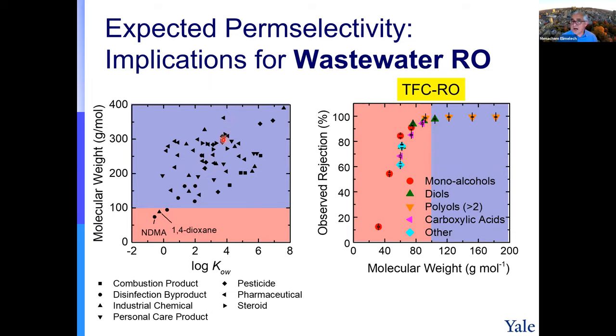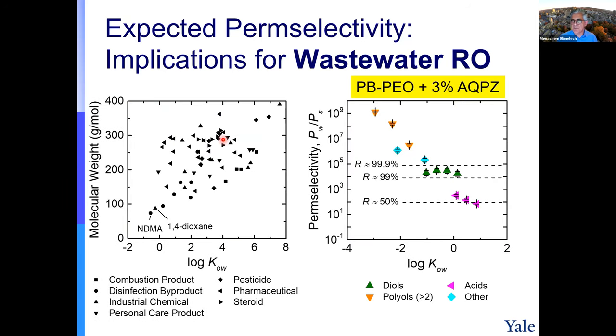Now let's go to our aquaporin-based membrane or biomimetic membrane. And this is the PB-PEO, the block copolymer with 3% aquaporin. And these are the measured perm selectivity of water over the solute selectivity. Again, rejection goes in this direction versus the KOW.